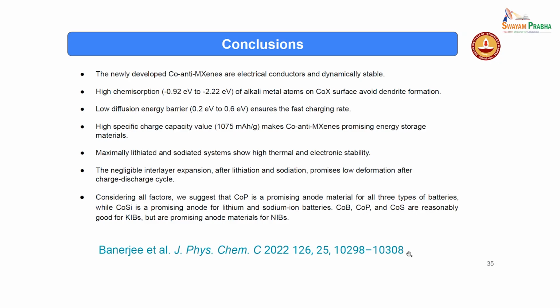And finally, we have seen that maximally lithiated and sodiated systems have high thermal and electronic stability, and negligible expansion. So considering all the factors, what we find is that CoP, cobalt phosphide, is a promising anode material for all 3 types of batteries, while silicide is promising for lithium and sodium. All these others are reasonably good. They are not extremely good, but they are reasonably good for the case of the other ones.